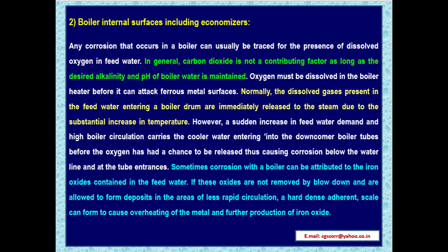And second problem, boiler internal surfaces including economizers. Any corrosion that occurs in a boiler can usually be traced to the presence of dissolved oxygen in feed water. In general, carbon dioxide is not a contributing factor as long as the desired alkalinity and pH of boiler water is maintained. Oxygen must be dissolved in the boiler water before it can attack ferrous metal surfaces.